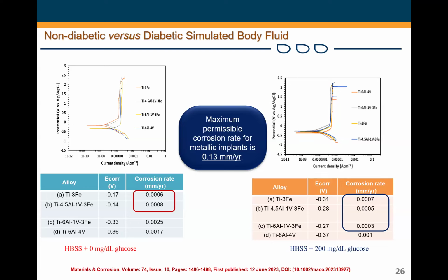But what we don't know is how iron is promoting the thickness of the titanium oxide. We don't know that, and this is one of the areas where we hope that we can find collaborators who can help us explain what is happening in that case. And the role of adding PGMs to titanium is well established. Molybdenum, tantalum, and niobium are well established in terms of corrosion performance and how the titanium oxide is formed. But when it comes to iron, even aluminium, there's still so much to learn in that space.